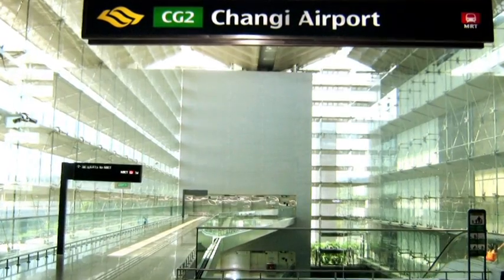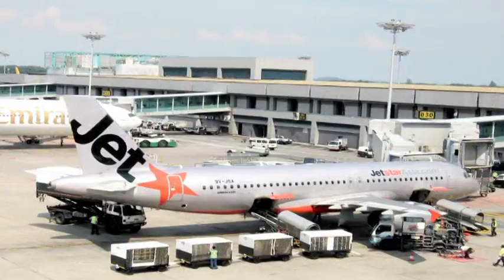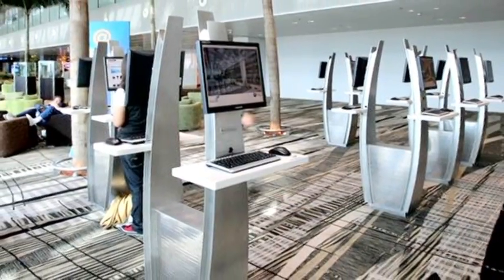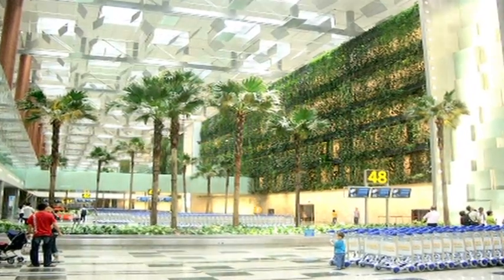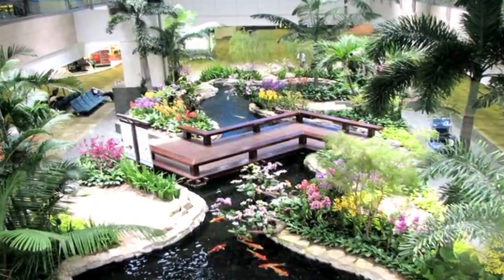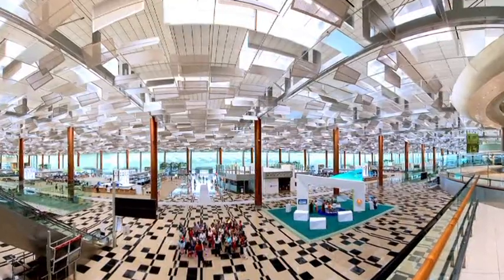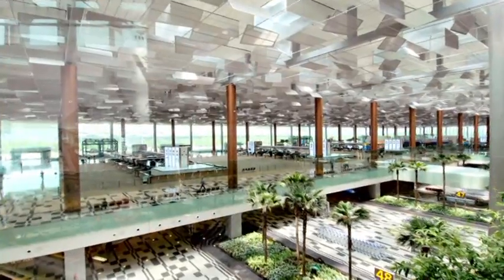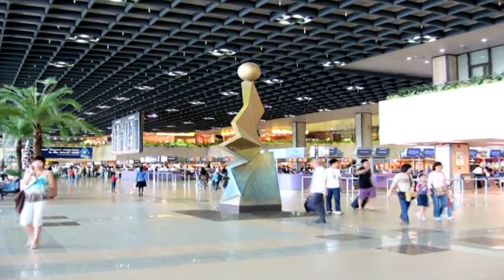For example, a coating thickness of about 50 to about 60 micron in rural atmospheres can make the objects last for as long as 50 to even 60 years. Singapore's Changi Airport, built 30 years ago, is famous for its works of art and in particular its man-made waterfalls, carved ponds and aquariums. The anti-corrosive protection of zinc has assured that these attractions are in pristine condition and will remain that way for decades to come.